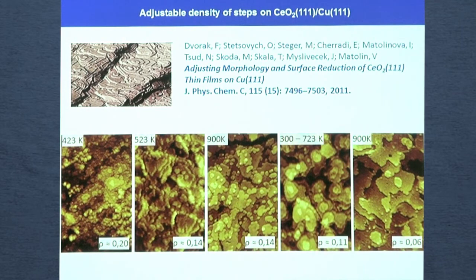The other important step is to control the morphology. Morphology means controlling the density of single atomic steps at the surface by scanning tunneling microscopy. So this is the image of CeO2(111) on a copper(111) substrate. And you can see that by changing the deposition parameters, annealing and so on, we can change the density of steps in a relatively large region. So it means that we can control the morphology and we can control the stoichiometry.